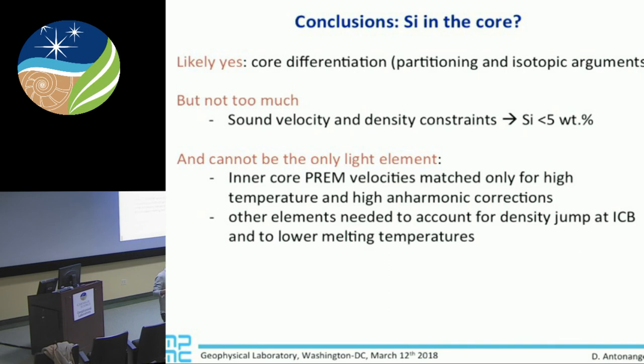Melting is something, for instance, where both silicon and sulfur reduce the density in a similar way. But silicon gets much stiffer bulk modulus, and silicon doesn't lower melting. So once we add an independent constraint, we can try to address this multi-element space with multiple constraints.